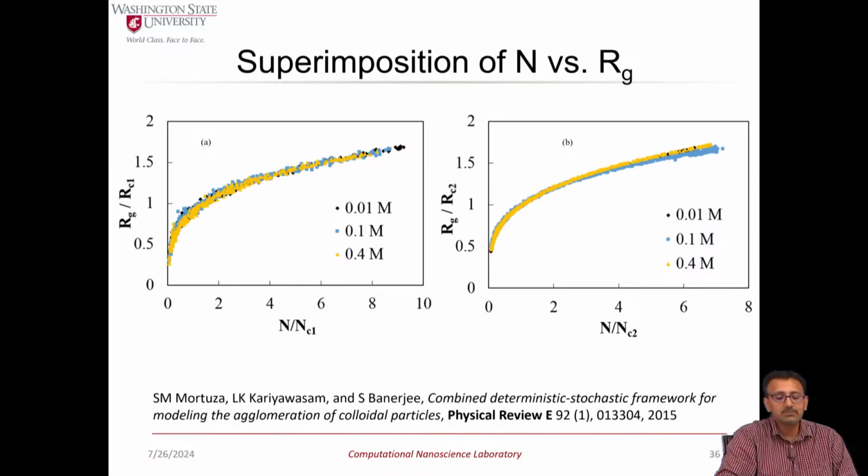The interesting aspect is that if we normalize it, all these fall on top of each other, which suggests that in terms of the aggregation process or clustering process, the physics is pretty similar. The salt concentration is not really playing a huge role here.